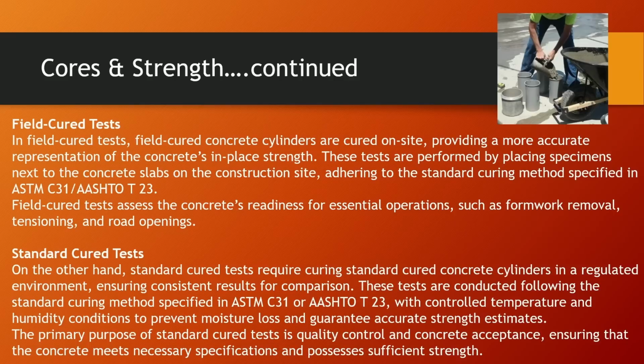Field cure tests. In field cure tests, the concrete cylinders are cured on site, providing a more accurate representation of the concrete's in-place strength. These tests are performed by placing the specimens next to the concrete slab on the site, adhering to standard curing methods specified in ASTM C31. Field cure tests assess the concrete's readiness for essential operations such as formwork removal, tensioning, and road openings. To me, with my background, I'm always a proponent for field cure tests.